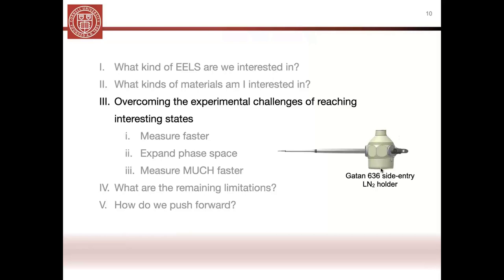That's where you put the cryogen. In this case, I'll be mostly talking about work with liquid nitrogen. And then your sample sits out here at this thin tip that extends into the microscope. One thing that's inherent to all of these side entry cryo holders is that there's a big thermal gradient between the cryogenically cooled sample, the cryo Dewar on the outside, and then the rest of the warm microscope room.